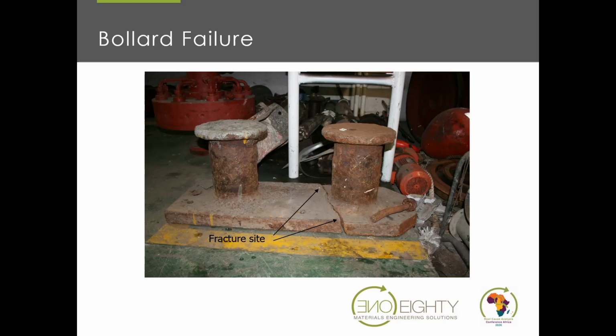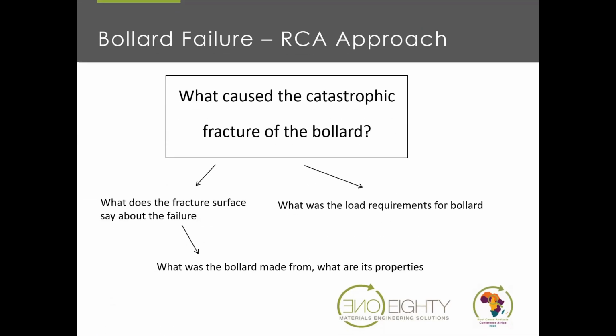And so we needed to go into a proper root cause analysis to determine the cause of failure. Unfortunately, I only received the bollard 4 or 5 years after the incident occurred, which is always very difficult, and had to work off fairly poor photographs from the surveyor that had been photocopied 10 times, and I'd gotten the 15th photocopy of his report. But in any case, we got around it and we got to the root cause. So this was our approach.